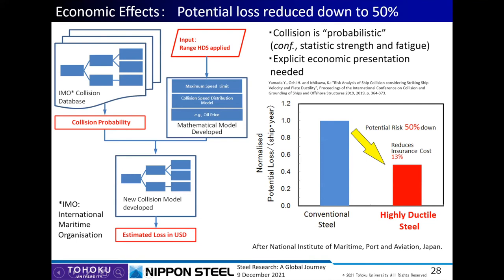And then in order to penetrate these new products into the market and spread in the market, we made some calculation of economic effects based on the existing collision accident database organized by the International Maritime Organization. With a combination of this database and a newly developed mathematical model, we estimated a financial loss in US dollars. By this calculation, we found that the normalised potential loss per ship per year that can be expected is almost half compared to the conventional steel.